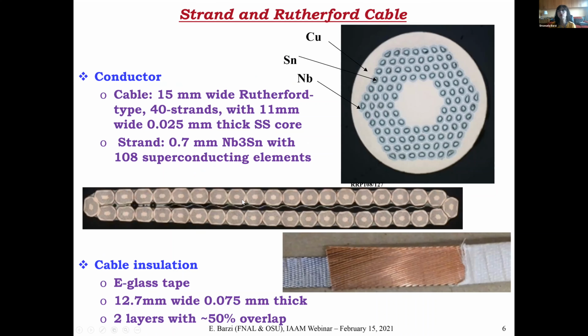It's made of 2 rows of superconducting composite wires. And the superconducting wire is this one, and it has a copper matrix in which these superconducting elements, niobium tin, are embedded. So practically, these little circles here are the tin rods. These are tin rods, and they are surrounded by dozens of very small niobium filaments. And when you receive the wire, it is not superconducting, it is a composite. But then you fabricate your Rutherford cable, this one, and of course you impress huge strains, and you go into plastic mode on the material.